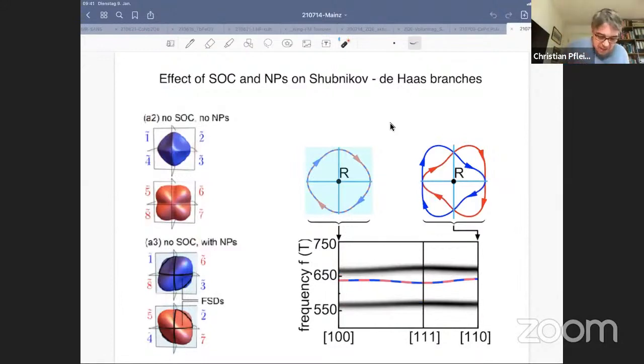And there's a consequence now for these Fermi surface orbits that the electrons or the charge carriers undergo, right? In a sense, what they do is that they switch, they don't stay on the inner circuit, right, or on the outer circuit, but because the wave functions are orthogonal at the crossing points, they will basically swap over to the other orbit, right? So we're basically showing this here, that we take basically this corner here, will connect with this part of the Fermi surface. So wherever they intersect, the electrons basically have to go onto the other side. And that's a direct consequence of the topology.